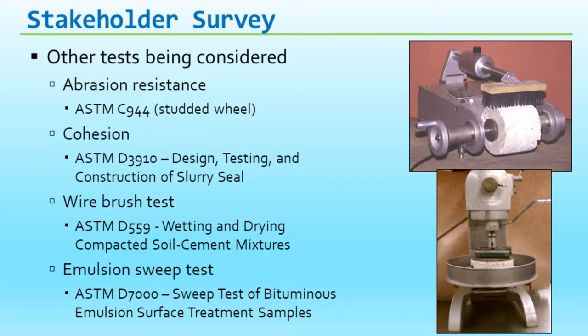Some raveling resistance tests. The most common one is what we call the F-150 test. So the guy sits in his truck, turns the steering wheel left and right. Does that rip the material up or not? Whether you use a Ram or a 150, there could be some issues with that. Truck full, truck empty, all of those sorts of things. And then some more formalized, ASTM rotating hose tests and that sort of thing. Abrasion resistance, studded wheel, some guys have looked at that as a potential. The cohesion, so slurry designs, can we adapt those tests?